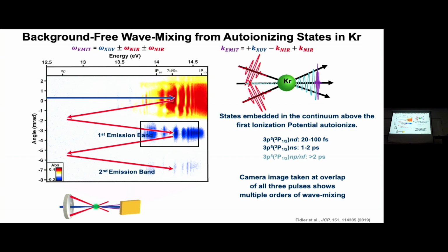But there are other forms of spectroscopies like wave mixing and so on. For example, you could do a four-wave mixing experiment where you mix an attosecond XUV pulse with two 800 nanometer pulses from a Ti:sapphire laser, called near-IR, and you could get new emissions that are born due to the interaction of the near-IR pulses with the XUV. And those can be what we call wave vector matched. So we have to match not only the energy, but also the angles, which leads to the momentum matching.